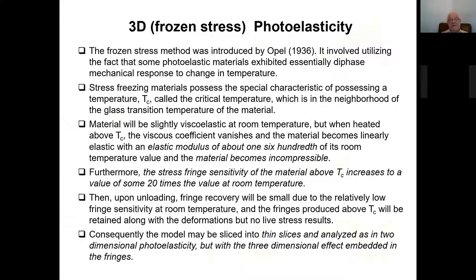Okay, now we'll go to 3D photoelasticity. 3D photoelasticity has been well known for many years, introduced in 1936. Essentially, you are doing the so-called stress freezing. This means that you have to reach a temperature, which we'll call the critical temperature. This critical temperature is close to the glass transition temperature of the photoelastic material. The important issue is that when you go through this temperature, the material becomes linear elastic, so you get rid of the viscoelastic coefficient.